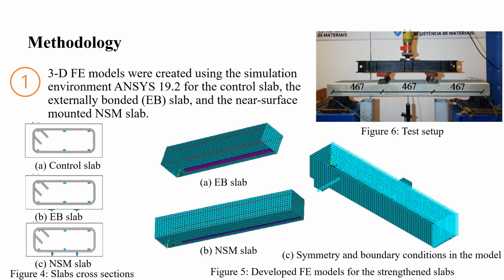under 4-point bending test at room temperature, and they also subjected the soffit of other strengthened slabs to ASTM E119 standard fire. As we can see in figure 4, the cross sections of the tested slabs.